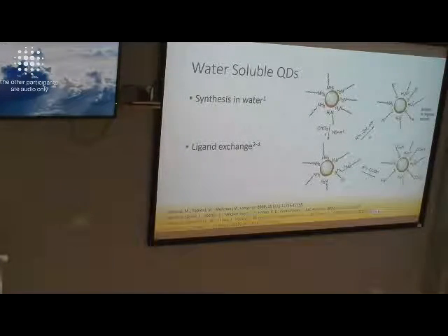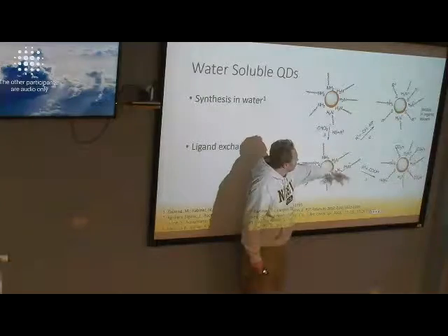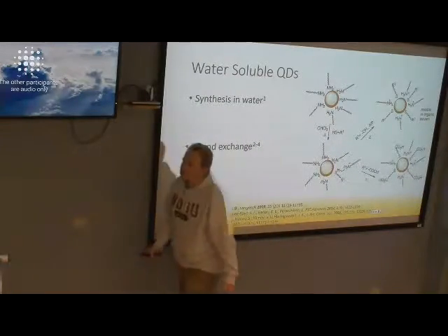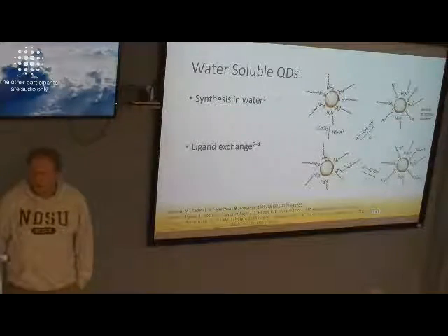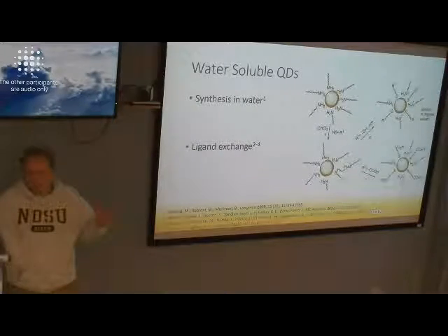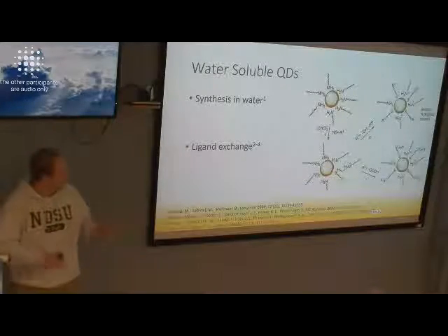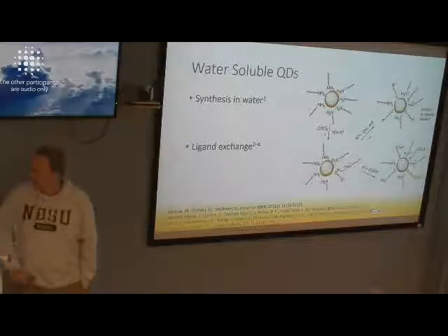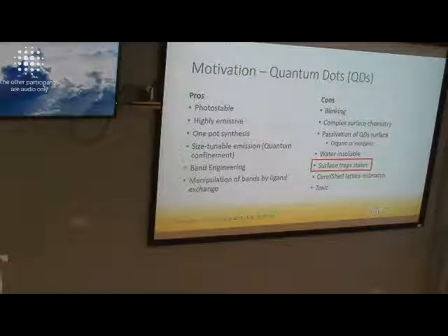Additionally, depending on the R group on the thiol, you can make it do specific things. There have been papers where you have two thiol groups and you can make a superlattice, where all your quantum dots are spaced evenly and very well ordered. But that is kind of how to solve water solubility in the quantum dot.